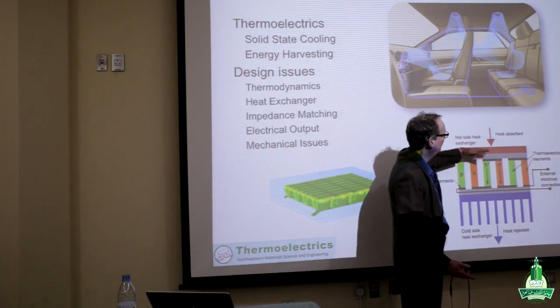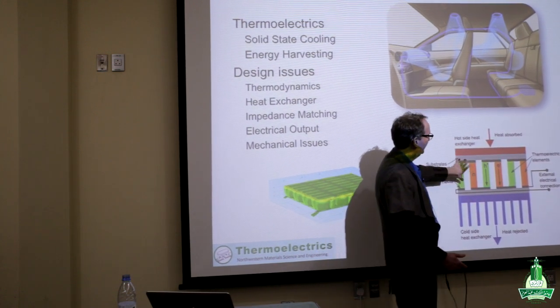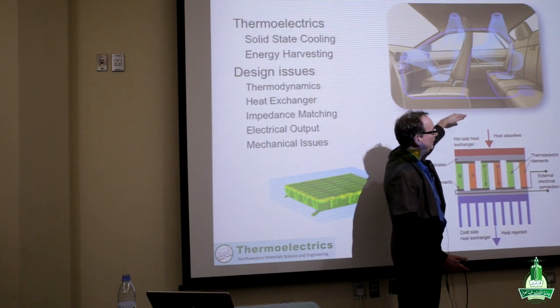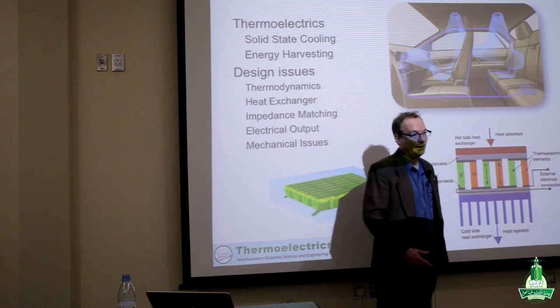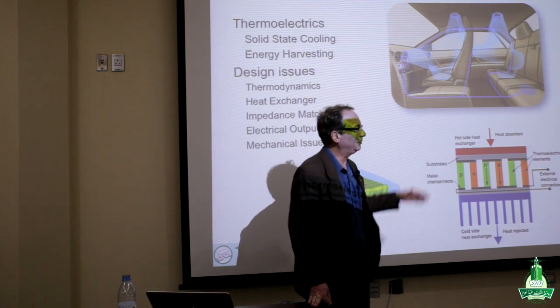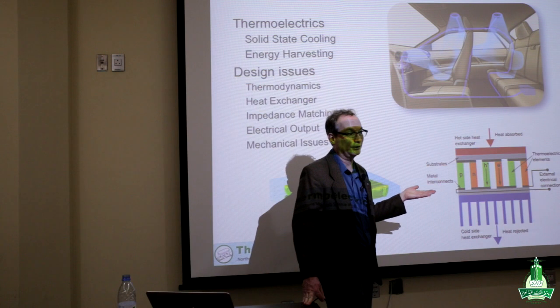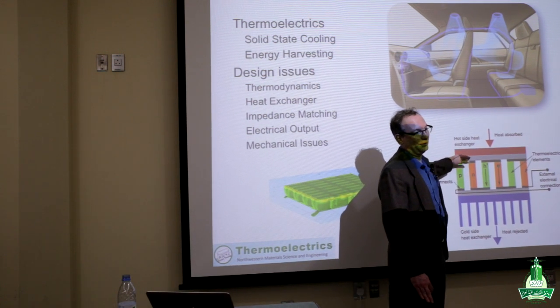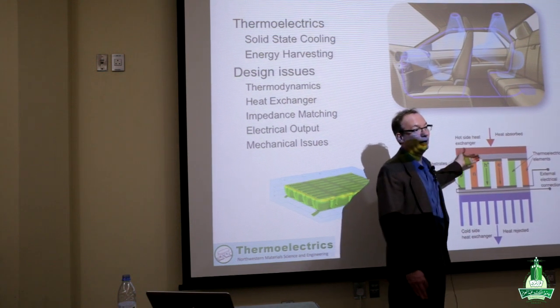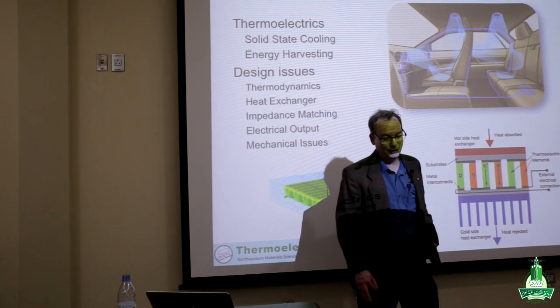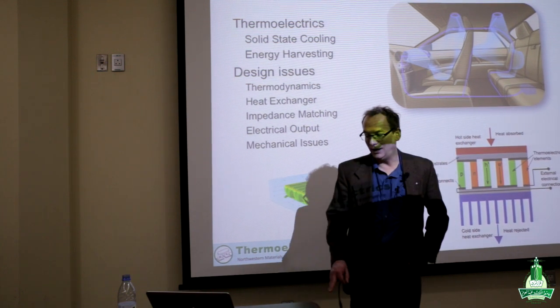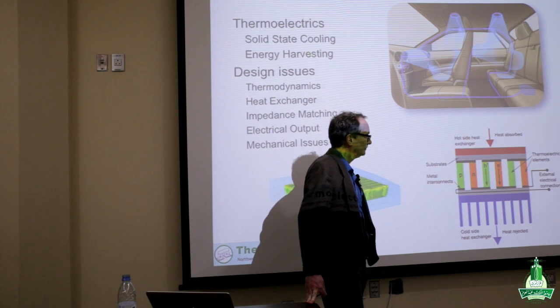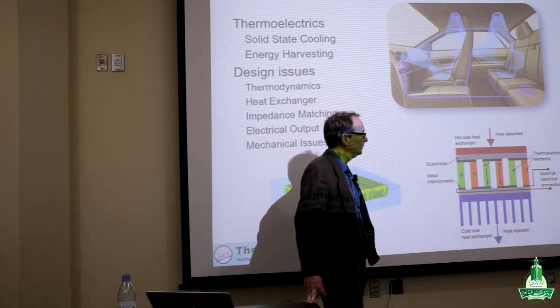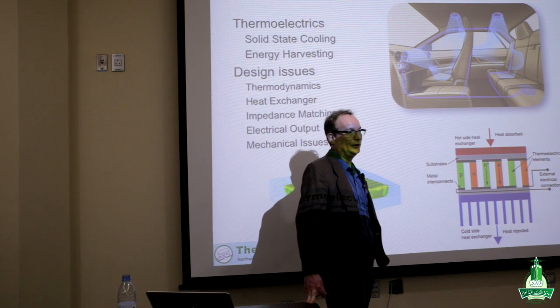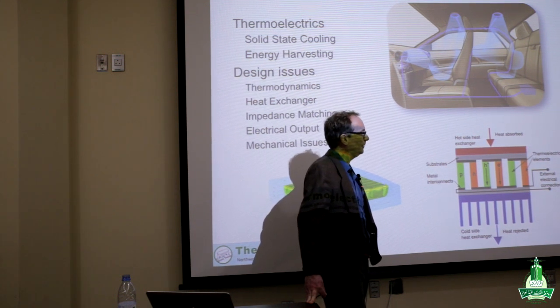If you just put the photovoltaic here as your heat absorber, then the thermoelectric would work best if it got hot, but the photovoltaic works best if you cool it. And it turns out that with the temperature coefficient of efficiency for a silicon solar cell, it's not really worth heating it up at all to use the thermoelectric. In fact, it would be better to cool the system to get more efficiency from the photovoltaic. Now, for other photovoltaic systems, that would be different. Large band gap systems that have a different temperature coefficient of efficiency, it would work.